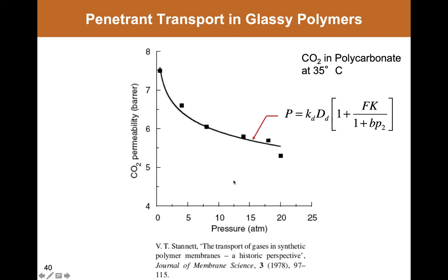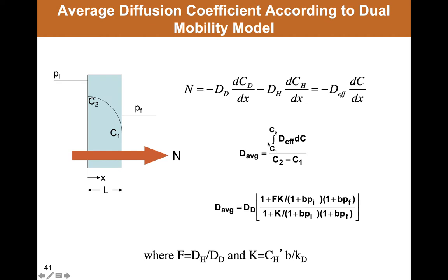Show one example of gas transport data fit to the dual mode model, and this is how you can get permeabilities that decrease with increasing pressure. It reflects that as the pressure increases, more of the gas molecules are in the Henry's law mode relative to the Langmuir mode, and they have different mobilities, and so both solubility and diffusion coefficients are changing as pressure changes in this case.